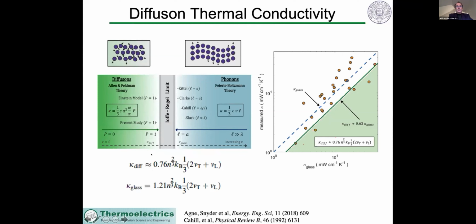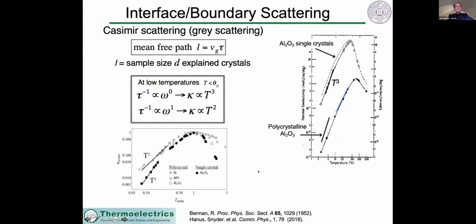In this Ioffe-Regel limit in between the two, we get very similar estimates for what a thermal conductivity should be. For example, a maximum diffuson thermal conductivity is quite similar to the Cahill model, which works well for glasses. And so we think that engineering to a diffuson limit could be a good lower limit for thermal conductivity.